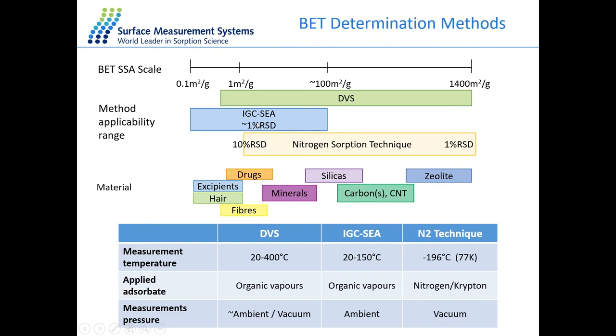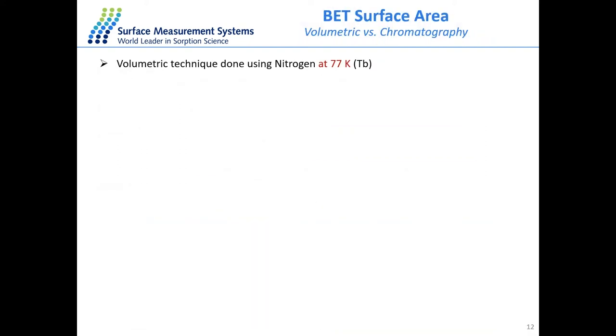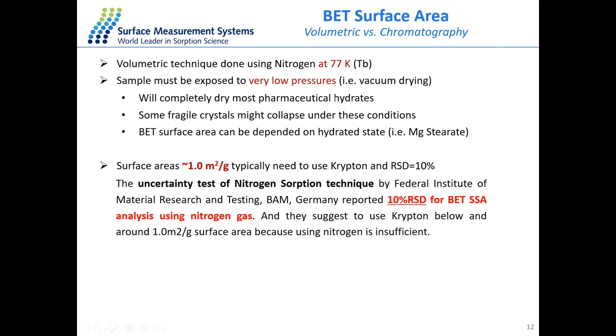And the IGC technique is especially accurate in the case of low surface area material. We can measure as low as 0.1 square meter per gram, still with very good reproducibility. The biggest difference between the two methods, the volumetric one and the IGC technique, is the condition of performing the experiment. With the volumetric method, we need to use nitrogen at liquid nitrogen temperature and also degas the sample under vacuum. In this case, some samples may already change structure, especially fragile or sensitive material. It will lose the hydration water along with the sample at dry condition, as well as collapse in the case of extreme conditions.